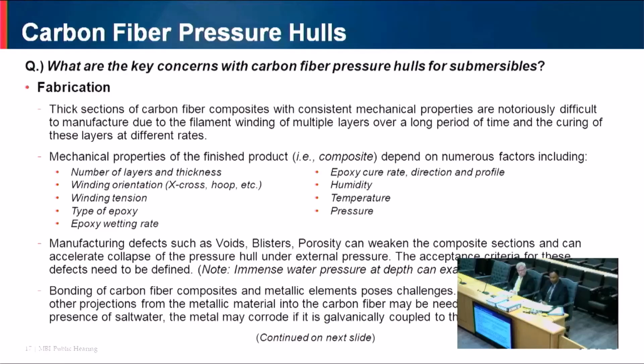Then curing the carbon fiber composite at the proper temperature is very critical. So if you don't follow the exact temperature profile when you cure the carbon fiber composite, then it will affect the mechanical properties. If you don't properly cure it, the mechanical properties can be degraded. So pressure is another important consideration when you cure your carbon fiber composite. So the composite can be cured at 1 atmosphere in a standard oven, or it can be cured under pressure in an autoclave. So autoclave is basically a pressurized oven. So the pressure will basically drive out the air pockets in the carbon fiber composite and will compress the carbon fiber composite. So you get a better product if you cure your carbon fiber composites in an autoclave versus curing it in a 1 atmosphere oven.